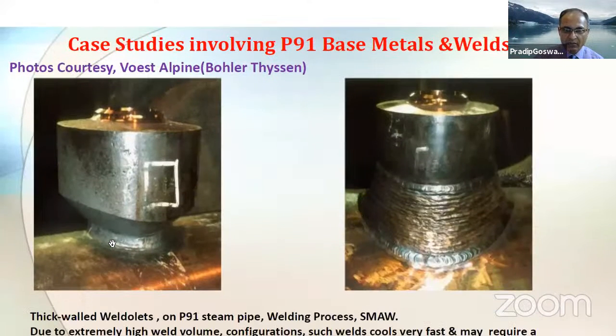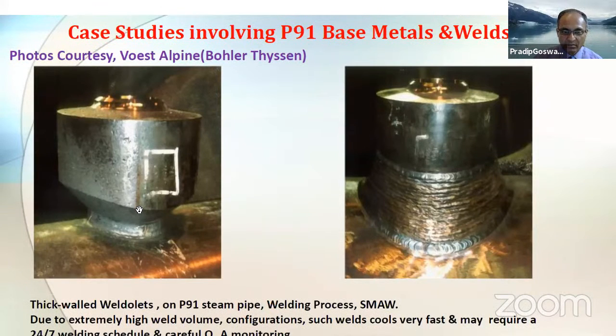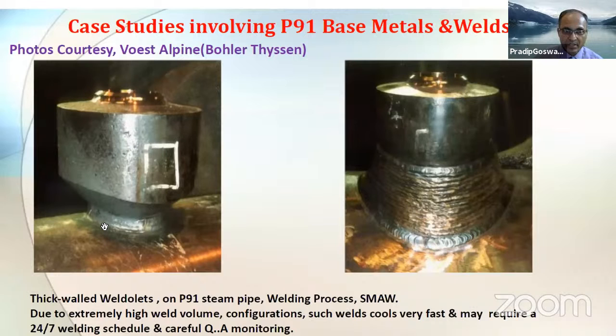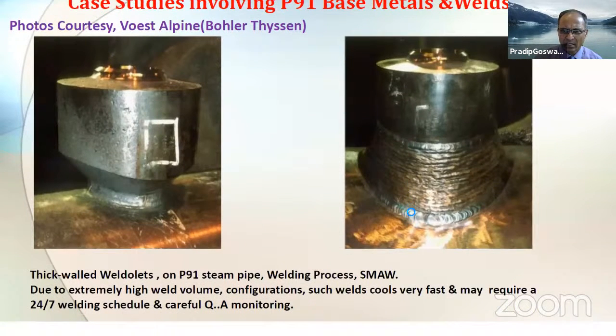So this is another photo of a typical, in welding engineers' terms, dreadful component, which can have dreaded consequences. Because here the welding involves a main steam pipe, which could be anything close to 3 inch or so, depending on the design, design temperature and the pressure involved, to a forged weldolet. And you see this is the groove, and this is a typical weld buildup or weld deposit. And the extent of welding can be enormous.